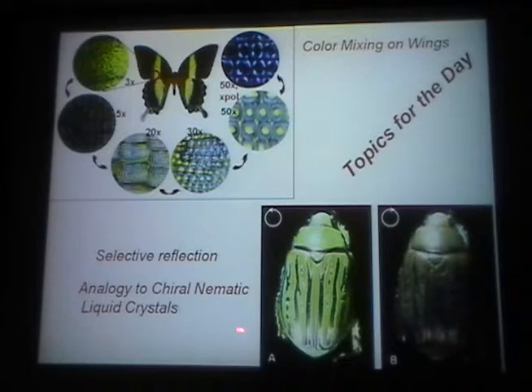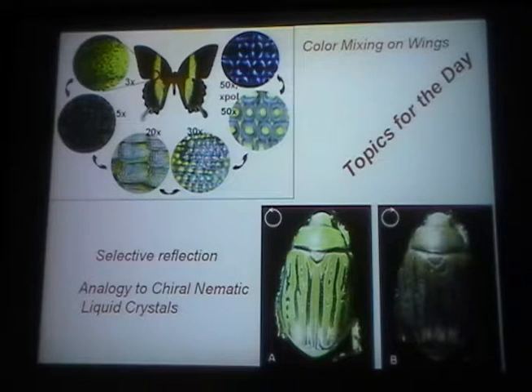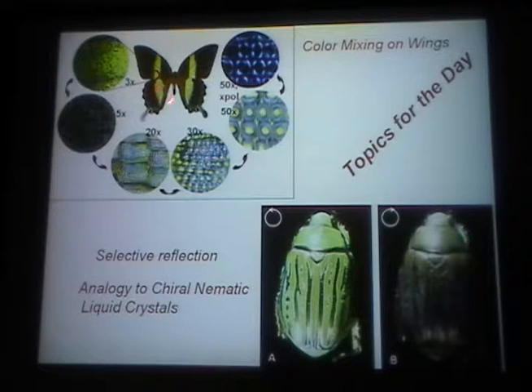I'll tell you a little story about this particular beetle. This appears to you, me, and anyone else — including probably the butterfly, although no one has ever asked what this looks like to a butterfly. The perception is green. But if you look at it with a microscope, what you find is a yellow reflection in the middle and blue at the edges. It actually additively color-mixes blue and yellow to produce the color perception that it is green. There is no green pigment and no structural element that produces green.